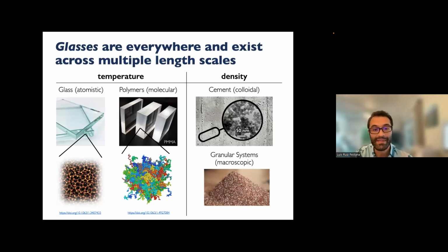and you get the glass. But there is this other set of materials that you can think about as jammed systems, which span maybe higher scales, and these include colloidal glasses, granular systems, other stuff, traffic, very abstract things that sort of follow the same dynamics. And in these other materials, the transition is triggered by changes in density. You reach a critical density where the system jams. And then once it jams, it does behave like a glass. And when I say it behaves like a glass, I mean that a similar theoretical framework can describe a lot of the dynamics seen in these very different systems. So in my mind, it's a very exciting problem.